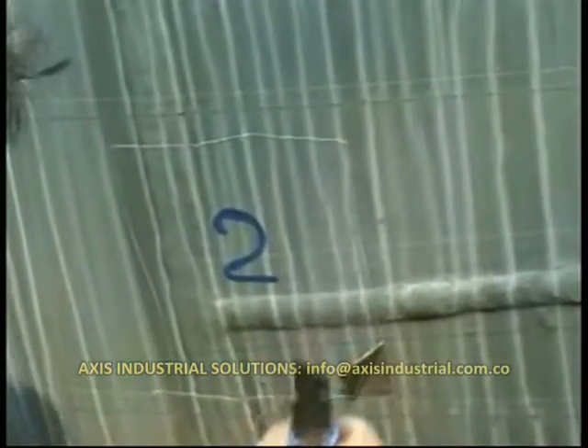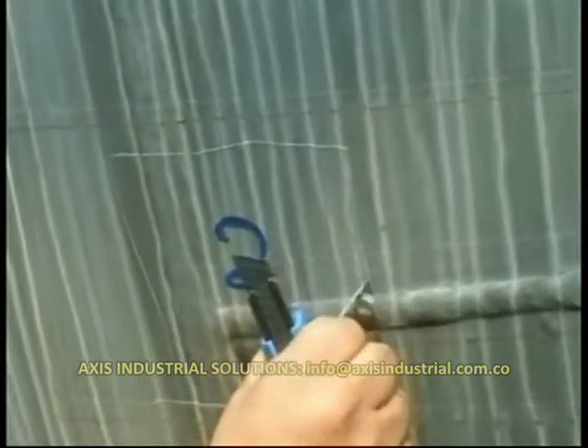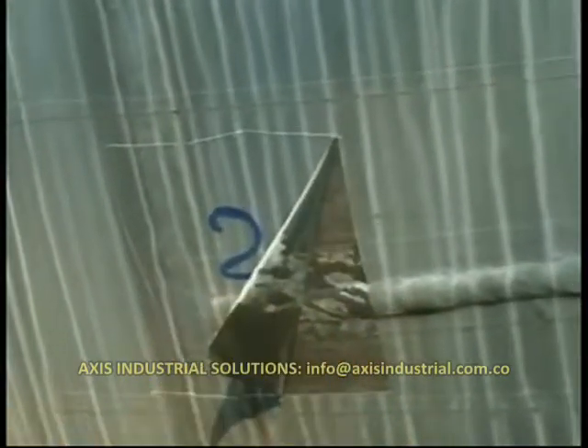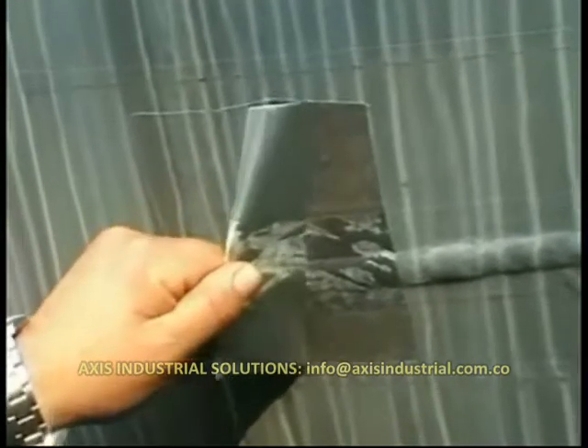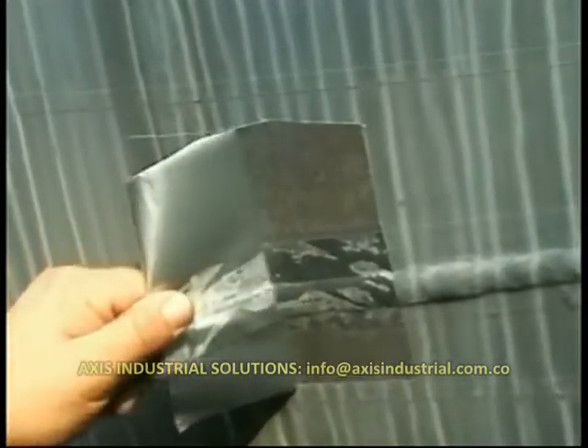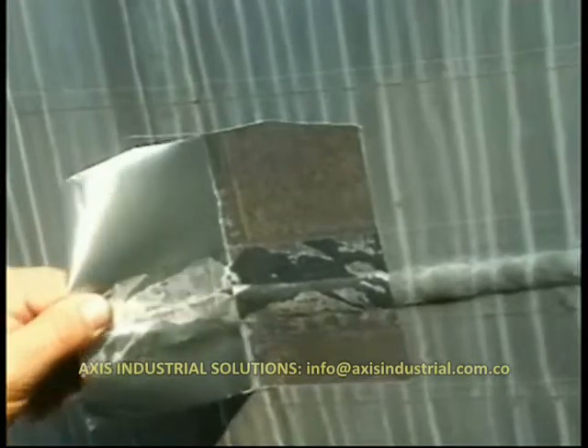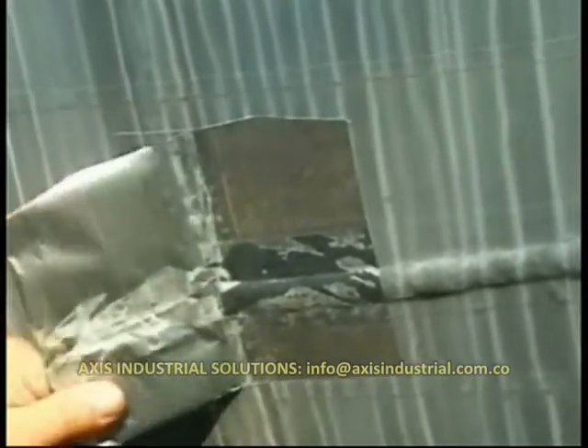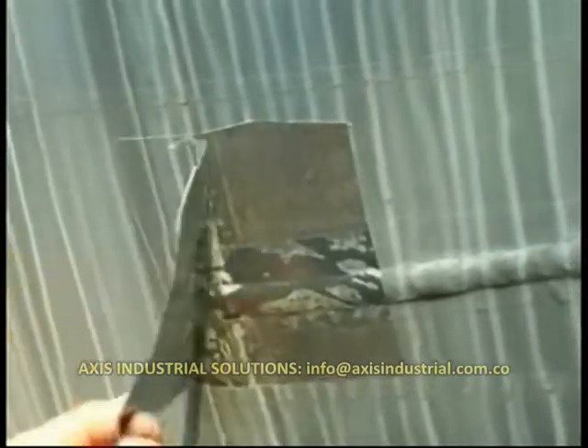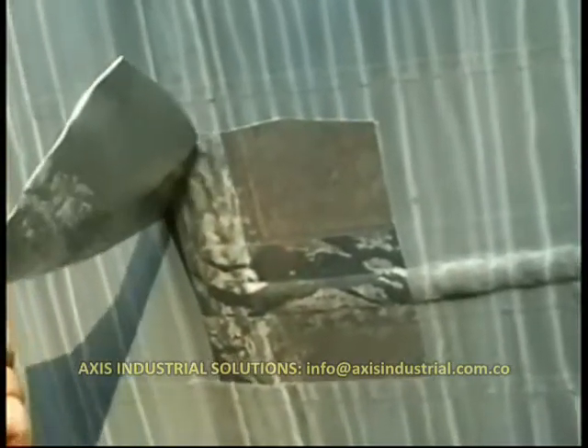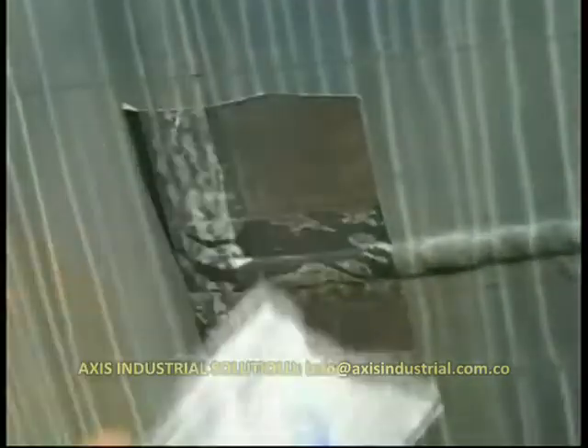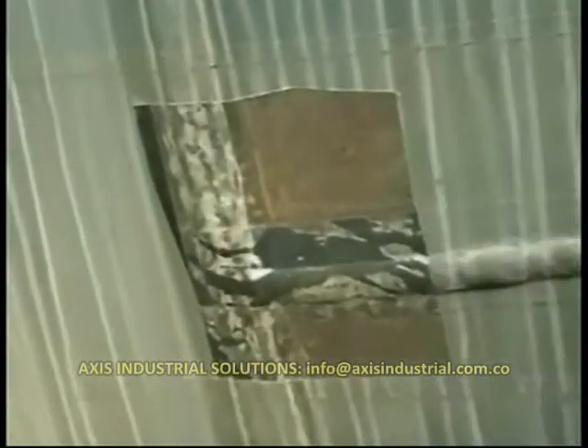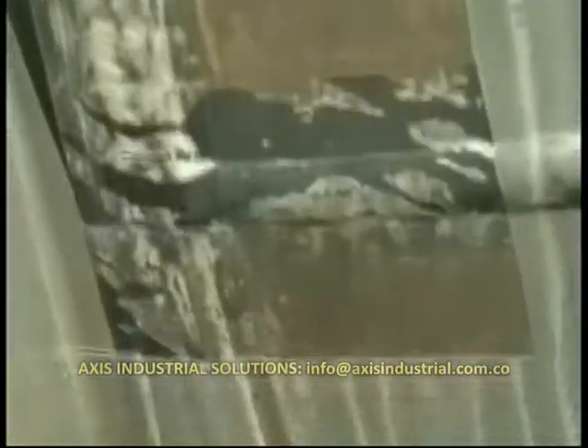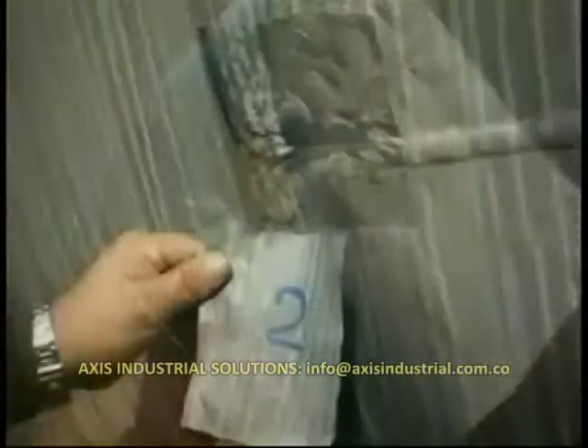This is a check of zinc tape on gas tanks after 20 years from original application. Samples of tape are removed and examined. As can be seen, the removal of zinc tape from the weld area shows the steel to be in perfect condition. There is also evidence that much of the electroconductive adhesive remains on the substrate surface. This is an indication that the bond between the zinc tape and steel is excellent. The sample zinc tape can then be taken away, the thickness measured with a micrometer, and the remaining life can then be determined.